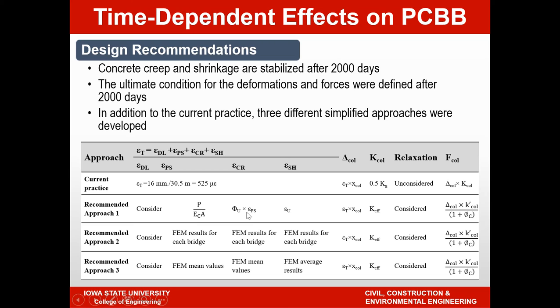And the creep strain is therefore taken as a pre-stress strain times the creep coefficient. You account for the ultimate or the total shrinkage strains, and you figure out the column forces based on the deformation you estimate. The second approach, we basically use the finite element results that we calculate for each and every bridge, but use a simplified analysis to determine the base shear forces, the top level displacement and the base shear forces.